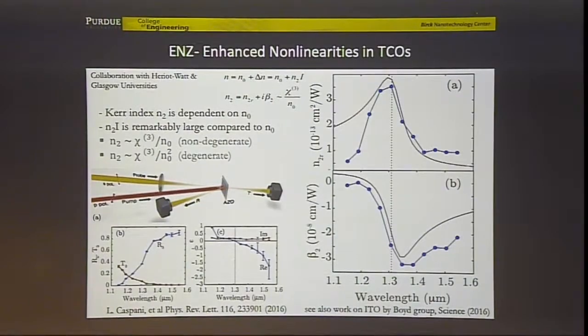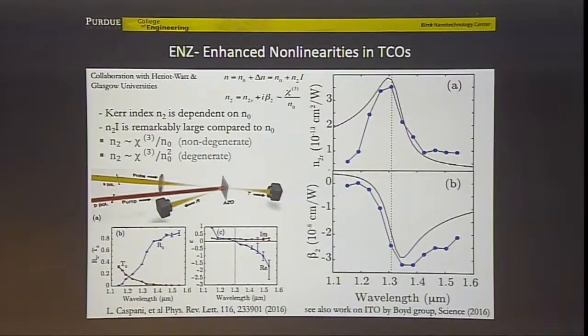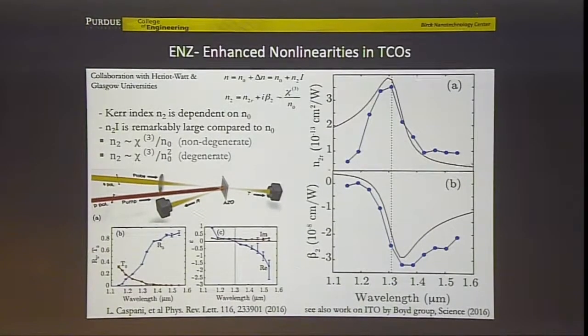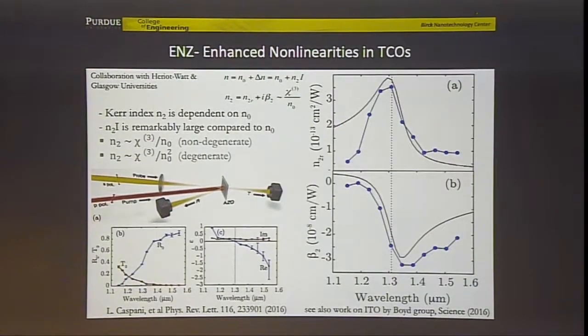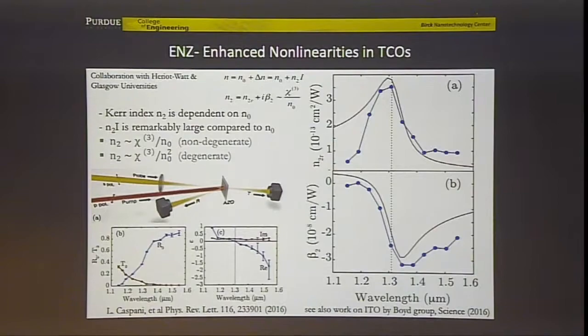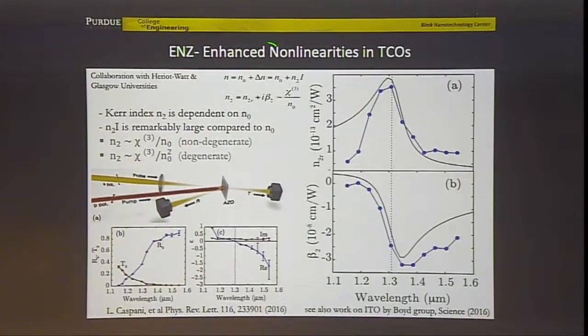And that includes the very important telecommunication wavelengths, 1.3, 1.5. Actually, it's up to us. We could design it. And look what happens at epsilon equals 0. Epsilon goes to 0, and the imaginary part is very small. It means that the refractive index, which is the square root of epsilon, becomes very small. And that's what we observe when we measure this n2 nonlinear term as a function of wavelength.